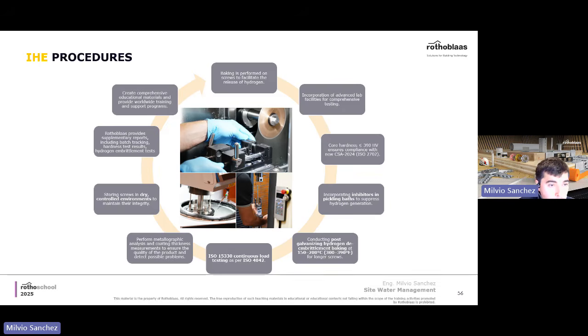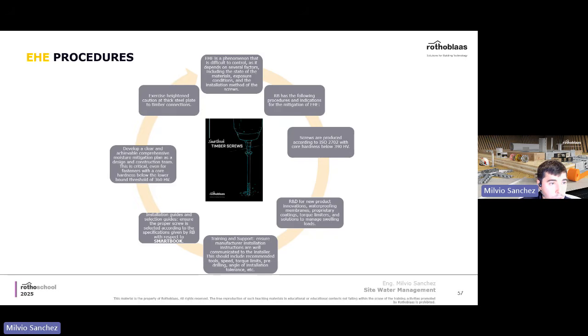To control internal hydrogen embrittlement, we have a very extensive quality control practice in our facility, where we have a core hardness set to below 390. We have inhibitors in the pickling bath to suppress hydrogen generation. We do post-galvanized hydrogen de-embrittlement baking on screws, and we manufacture according to ISO 15330.